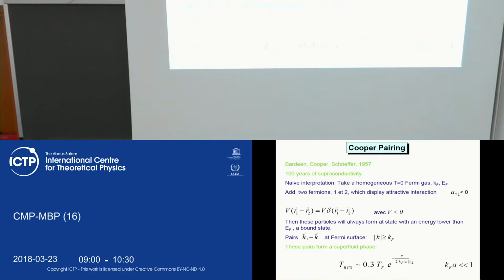In particular, the same kind of superfluid state is now observed in ultra-cold gases in optical lattices, where, as you may see, since the coupling constant is attributed to the Fermi momentum and the scattering length, it has nothing to do with phonons. The mechanism is purely electronic. However, the same type of BCS state can be observed, and what one can see from the fermionic superfluid state in optical lattices is that, first of all, the temperature of the superfluid or superconducting transition is 0.3 of the Fermi energy. So it's no more the Debye frequency which stands in front of the exponent. And then the exponent is exp(-pi/(2 kF |a|)), with a the scattering length. You may also see that if the scattering length goes to infinity, this is the so-called unitary limit.